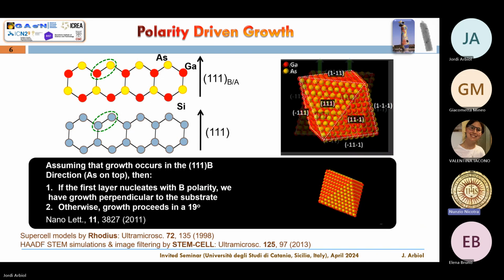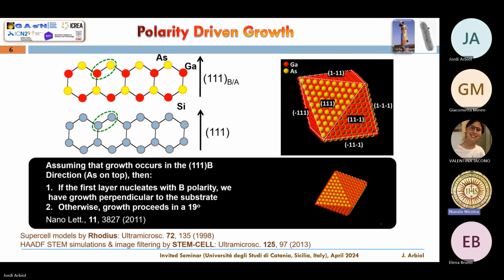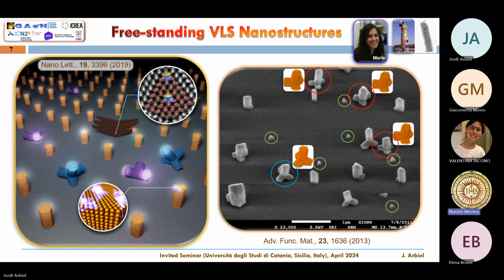But if we invert the seed that is growing the first time, you will not be able to grow a vertical nanowire because this facet on top will be terminated in a cation and then it will be forbidden. So instead of that, what you can see is that there are 3 other facets available, the ones terminated in, let's say, yellow for the anion, where it will be possible to grow this material. In this case, what you will get is a tripod, because instead of growing a vertical nanowire, you will have 3 different facets available for the growth. And this is what we tried to investigate with all these different facets.